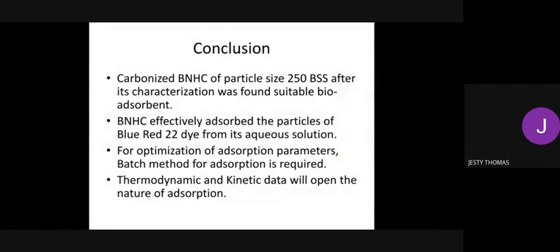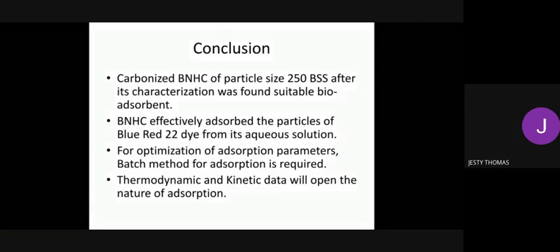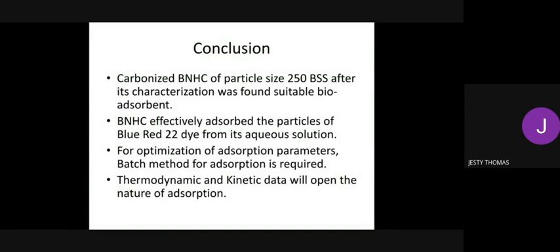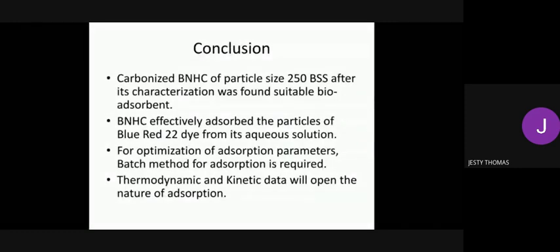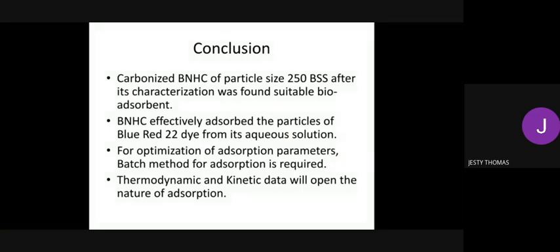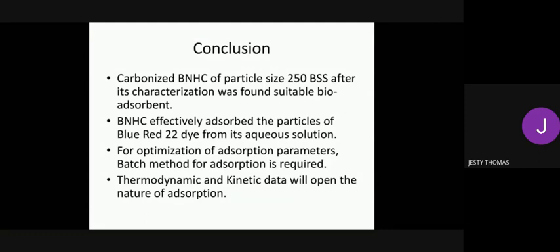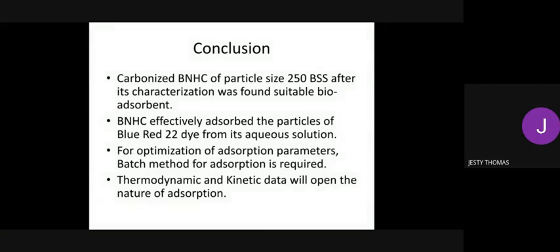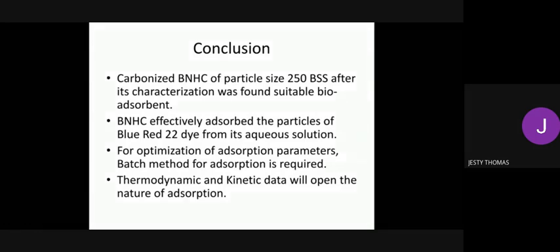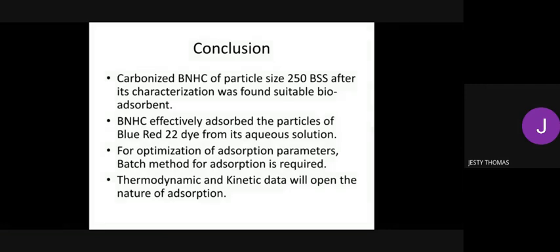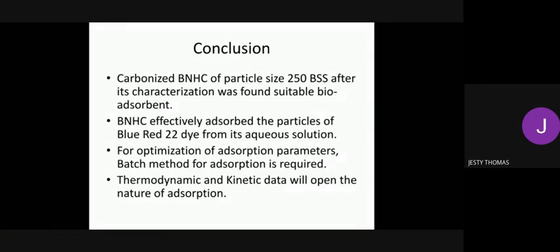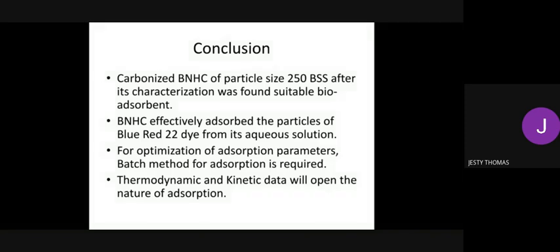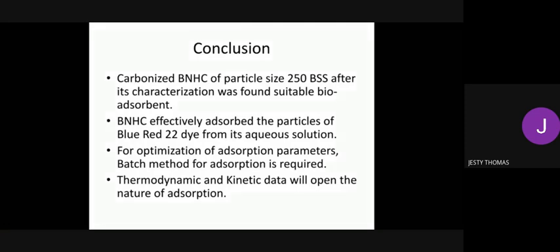These physical properties were studied, and in the conclusion we mention that BNHC, that is betel nut husk carbon, after carbonization was found suitable for the adsorption process. So we can say that it is a successful adsorbent, and BNHC has effectively adsorbed the particles of blue red dye 22. There are some other parameters that we mentioned in the steps for which optimization is also required. We can carry out batch methods of adsorption, and for a detailed idea of the nature and mechanism of adsorption between BNHC particles and blue red dye 22, we have to study the thermodynamic and kinetic data, which will offer a further attempt.